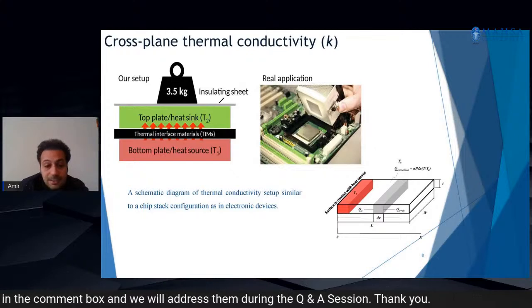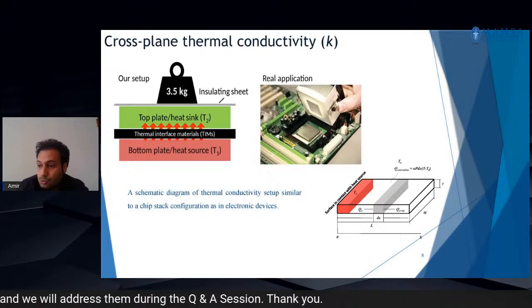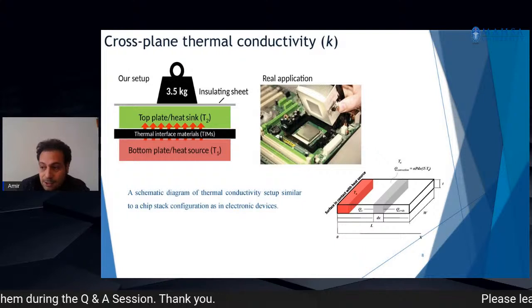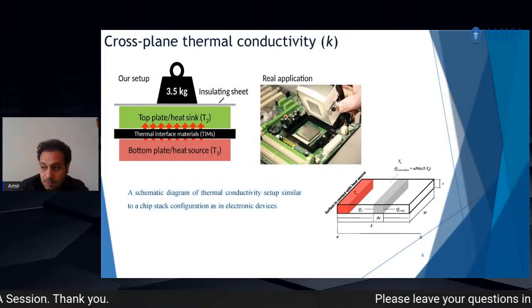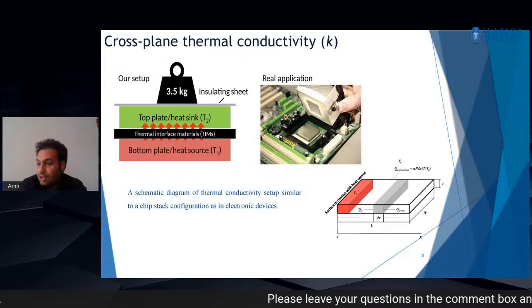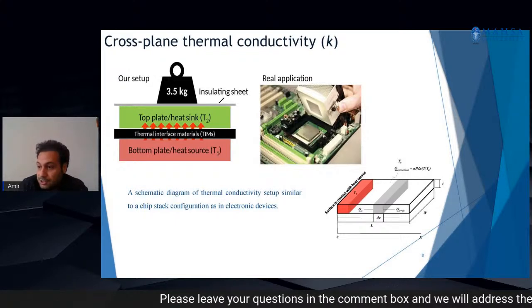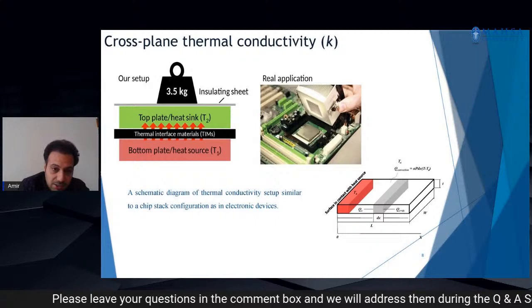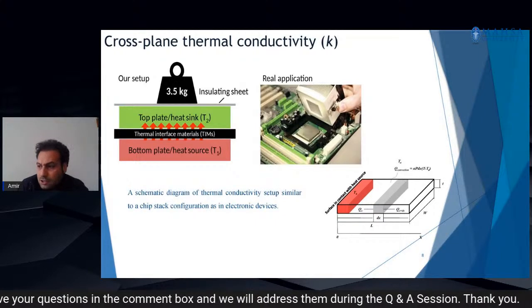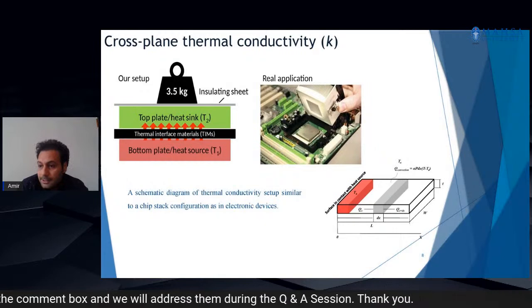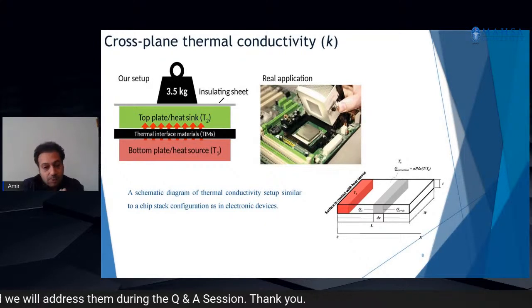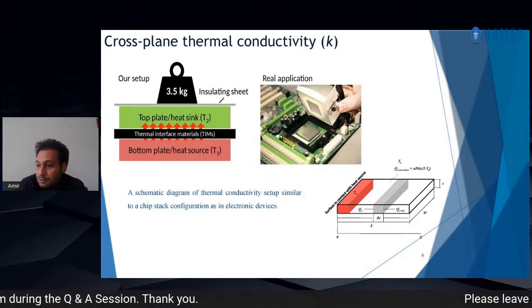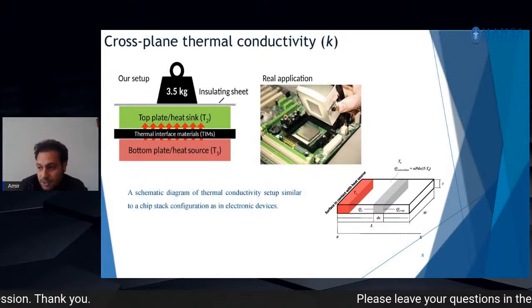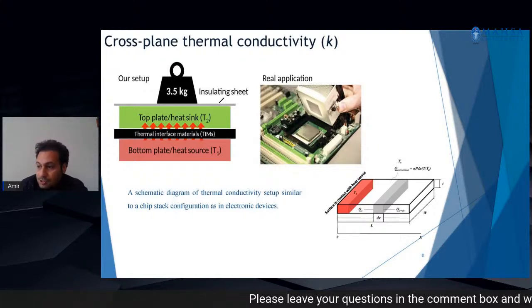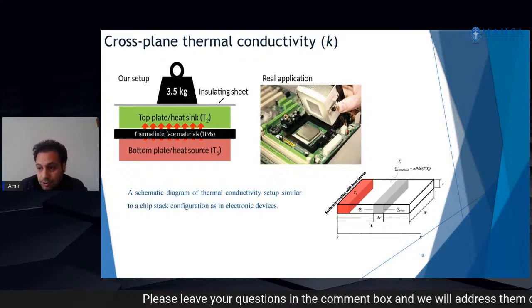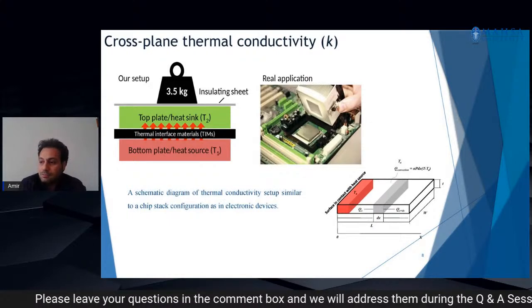So you can see here we are using two 1 centimeter thick steel blocks stacked on top of each other. In the next slide I will show you the real image. They are around 4 by 4 centimeters square, and the nanocomposite was sandwiched between the blocks under ambient conditions. Continuous heat is supplied throughout the duration of the measurement by the hot plate to the bottom metal block.